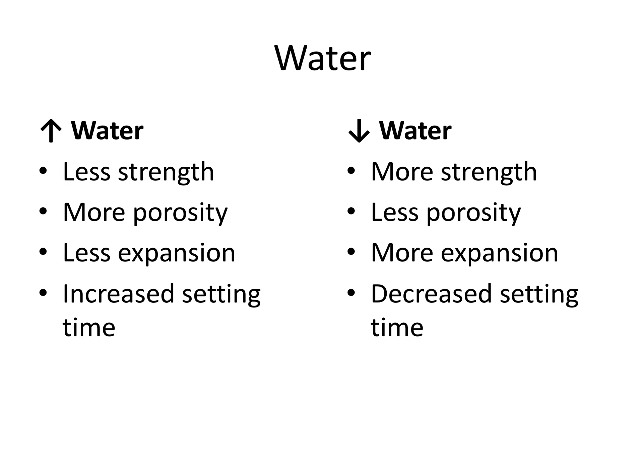You want to stick as close as possible to the water-to-powder ratio mentioned on the bag of gypsum powder, but you can adjust the amount of water. Just like we talked about in the impression materials video — how we can manipulate setting time — we can also manipulate gypsum setting time by increasing or decreasing water. A thin mix will increase the setting time and decrease the amount of expansion the plaster or stone experiences as it sets. The exact opposite is true for a thick mix. Memorizing one column means you just remember the opposite for the other.